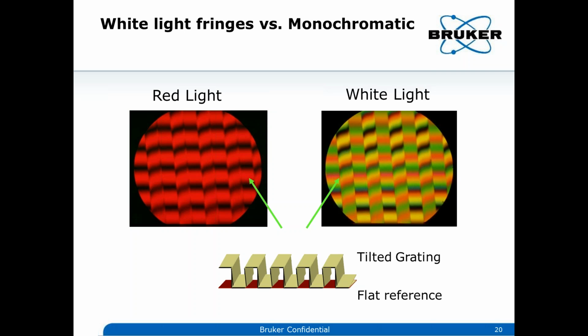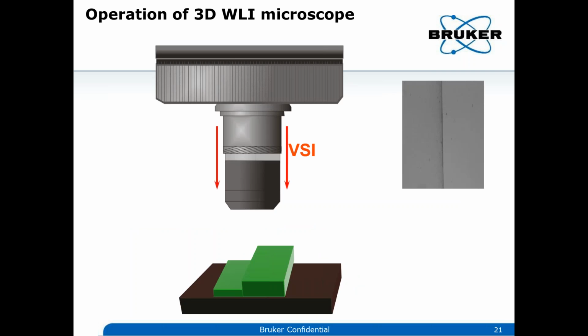So in general, if you have very rough surfaces, the white light interferometric technique is very accurate compared to the PSI technique. The PSI technique is limited up to lambda by 4 roughness. So if you use a green light, which is typically what we use, the wavelength is about, say, 560, so your roughness can measure up to 140 nanometers. You can safely measure. So here is a video of how the VSI technique works.